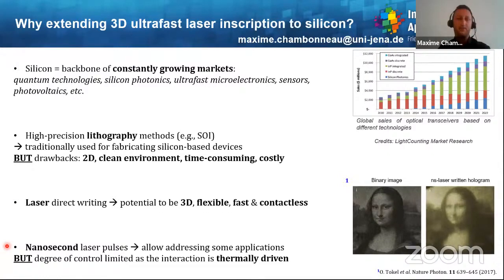To date, for laser silicon interaction, especially, nanosecond laser pulses can be used, and they allow addressing some applications. As you can see here, there is a binary image of the Mona Lisa from Leonardo da Vinci, and this is what can be written inside silicon, and this is the resulting hologram written by nanosecond laser pulses. Well, the main problem for nanosecond laser pulses is that the degree of control is somehow limited by the heat, and the interaction more generally is thermally driven.